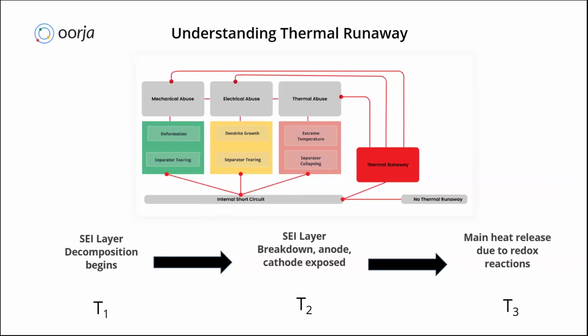And because of these various triggers, the internals of the cells might behave differently. For example, we know that whenever we use cells under very cold conditions, like 0 or sub-zero temperatures, or with high C rates, the lithium plating is going to be very high in the cells. Now, if you keep on using the cells with poor thermal management, rather than maintaining the pack at 25 or 35 degrees Celsius, you operate the pack around 0 degrees Celsius, then the lithium plating is going to get accelerated.